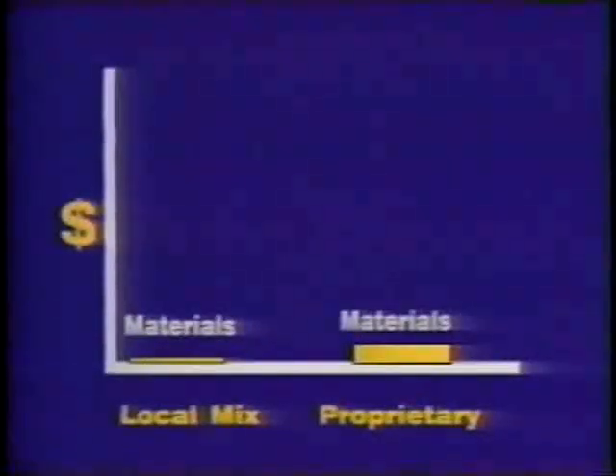2 material types were used: conventional local mix asphalt and a proprietary mix. The proprietary material cost per patch was more than 3 times the price of local mix. Labor cost was the same for each type of patch, a little less than $7. The average lifespan of the local mix asphalt patch was less than 4 months, while the average lifespan of the proprietary asphalt patch was more than a year.